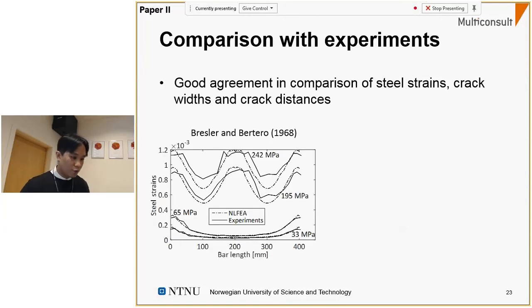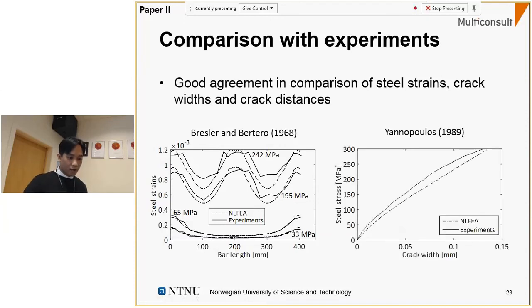We can show you from a comparison of one of the experiments, which was from Bresler and Bertero, where they measured the steel strains at four different load levels. And we see here that there's a relatively good agreement between the experimental steel strains and the steel strains obtained from the nonlinear finite element analysis at all four load levels. We also compared the crack widths with the experiments conducted by Yannopoulos in 1989, and we saw that the development of the crack widths with the steel stresses is also in good agreement.